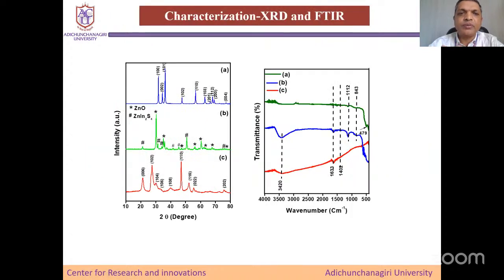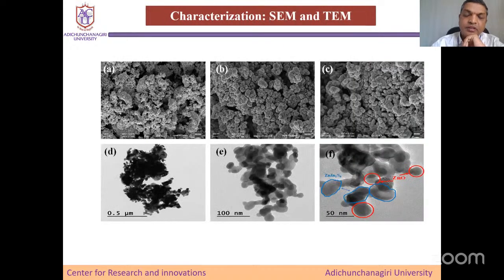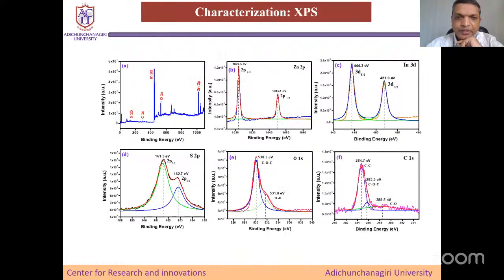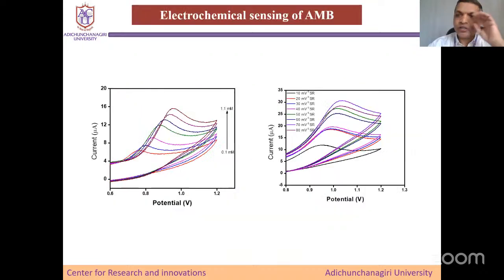So this is to confirm the nanoparticles, zinc oxide and zinc indium sulfide nanoparticles. And this is the transmittance, which confirms the presence of the composites. And this is the structure you can see here. This is the complete nanostructure. All the particles are around 100 nanometers. And this is the XPS spectra in order to confirm the formation of the composite. And this is very important, you can see here.